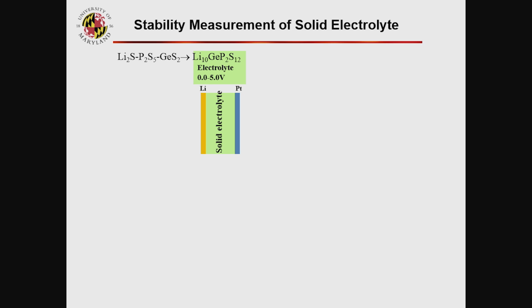But when we measure the capacity of anode and cathode, we use this kind of design. When we measure a material as anode or cathode, if they are insulators, we normally mix with carbon. Sulfur, you have to mix with carbon. Then you show the performance. So we mix the carbon and the LGPS, put in the liquid electrolyte, and then we get a window at the anode and a window at the cathode. So it looks like the difference is not because we sintered to form a new phase. The new phase is really just a little bit of potential, but the lithium sulfide is still there. So we think the problem is that the technology we used to measure the stability is different.